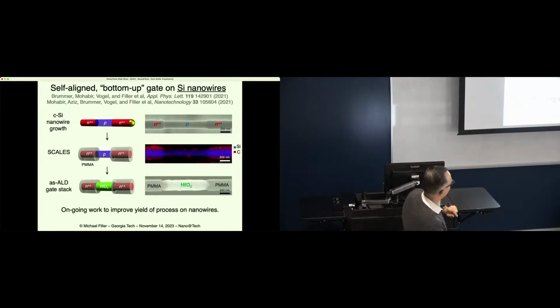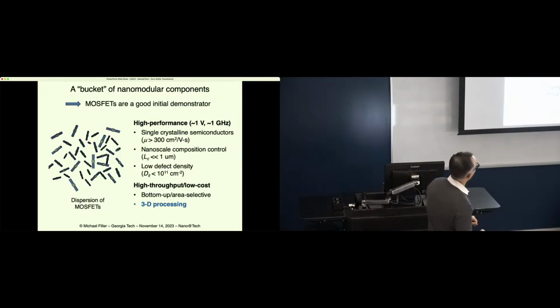And when we do our selective hafnia process, we can grow these coaxial hafnia films around the region of the nanowire that's the lightly doped channel region. So this work is ongoing. We continue to work through a bunch of yield challenges and understanding how a nanowire is a lot different than a wafer. They're both silicon, but the morphologies and surfaces and structures are enough different that we have to work through those complexities. But we're on our way.